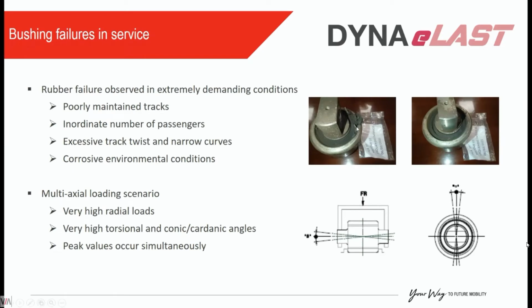So a couple of pictures of the failure mode that we've observed. To be honest, this is not very common. It occurs in very extreme conditions, usually a combination of all of these. So you have poorly maintained tracks, a lot of irregularities, very hard on the train and on the suspension, and an inordinate number of passengers. That's also very important because we are talking about 10 plus passengers per square meter. My first question was, how do you fit more than 10 people in a square meter? But apparently in some projects, that's something that does occur.